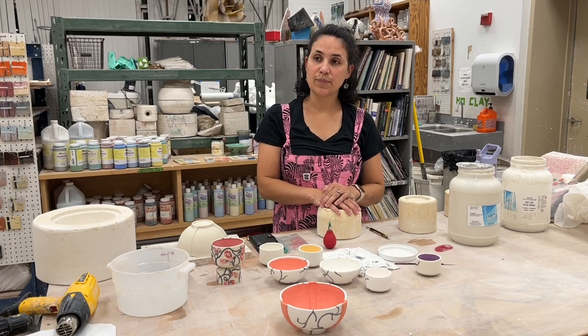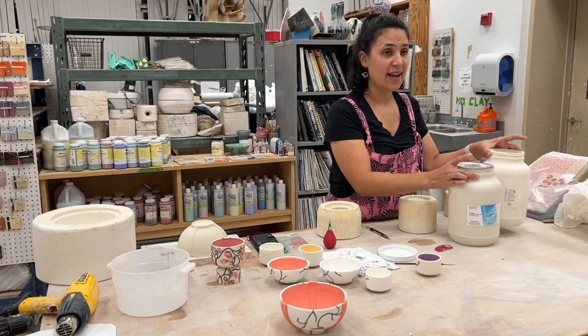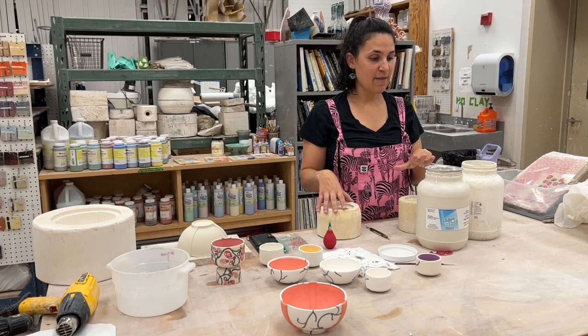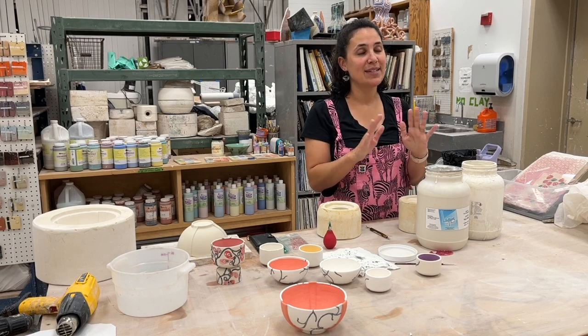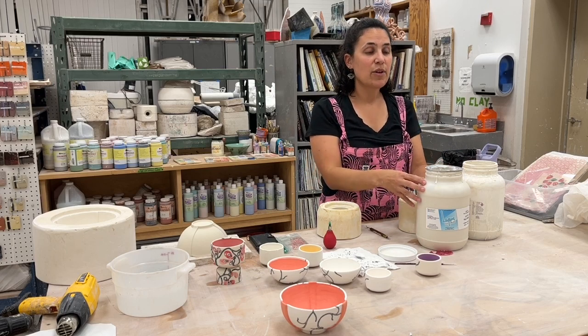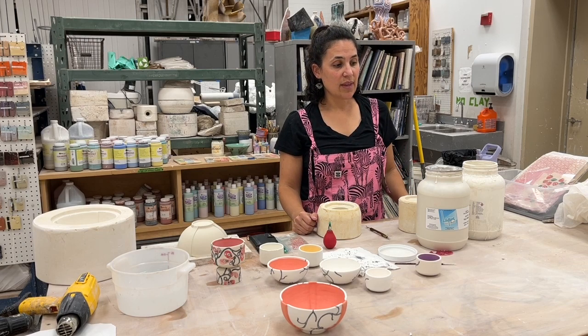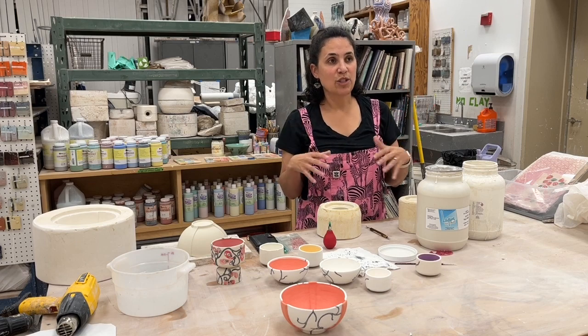When you remix all your scraps, are you using tap water or distilled? Distilled water. Then you sieve it — yeah, I use the same strainer and go back and forth between two containers. I could probably test specific gravity more and try to have it at a specific ratio every time, but I don't. As I pour from the bottle and pour back in, it's thickening because I'm drawing moisture out of it every time, so sometimes I have to add some water mid-session and mix it up.